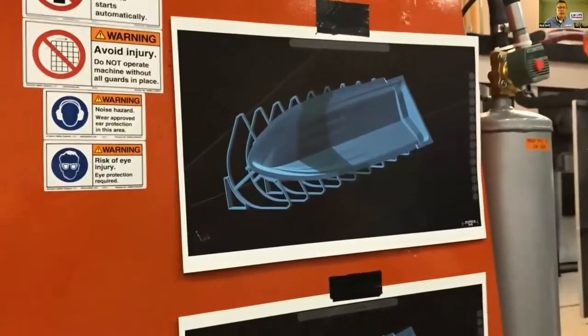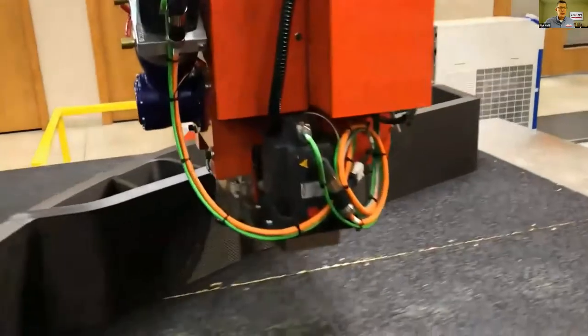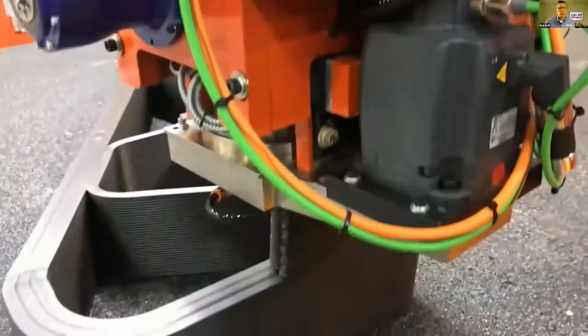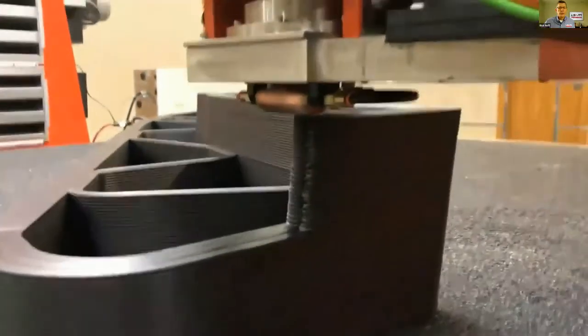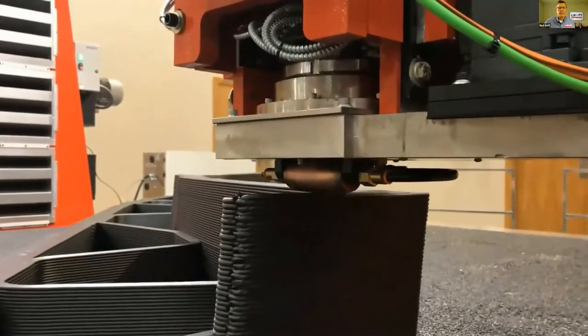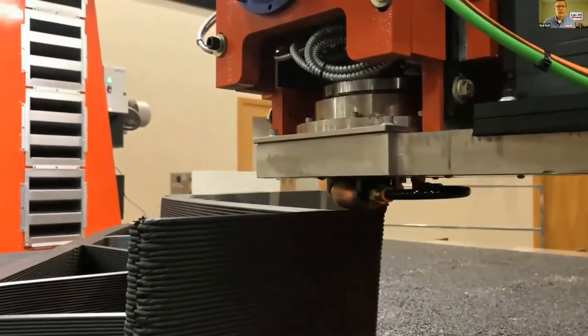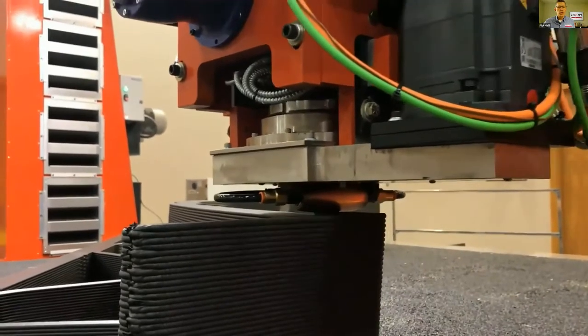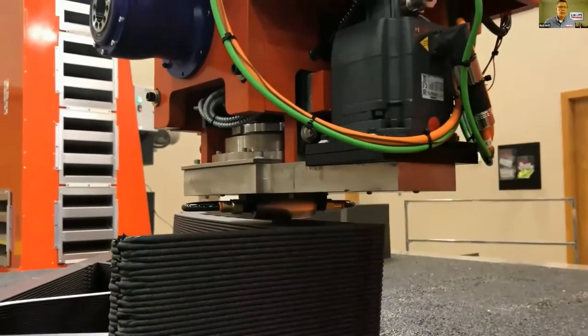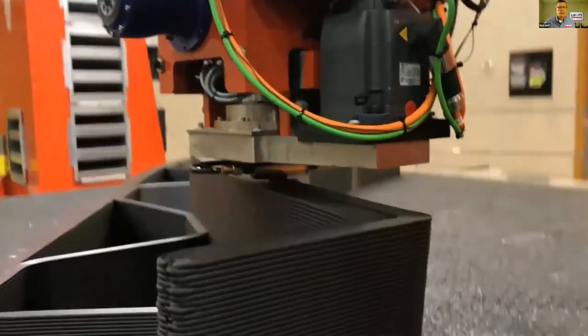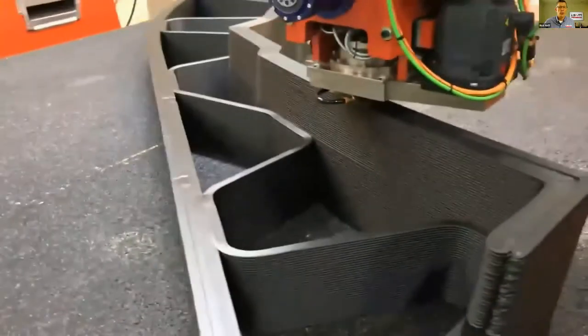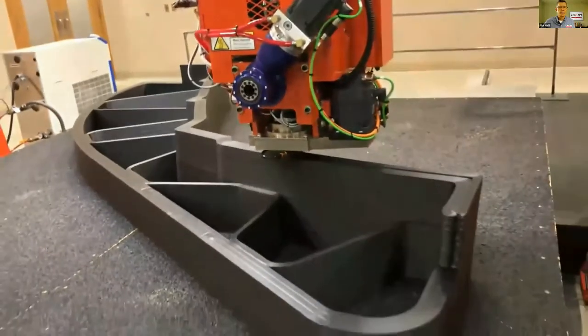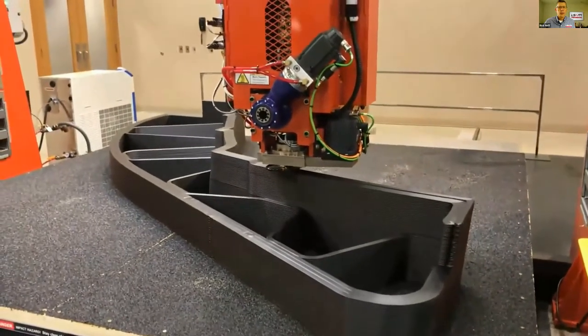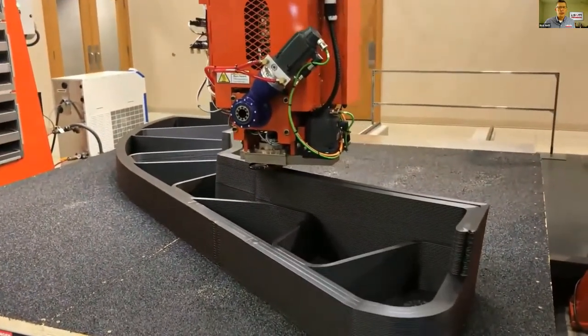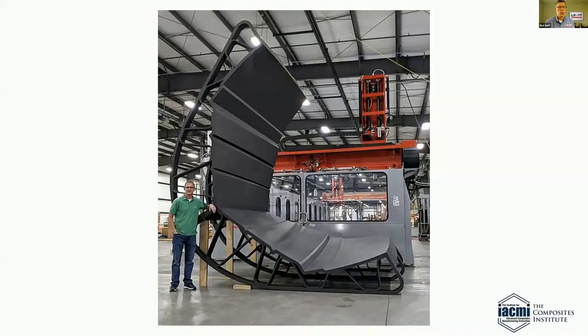This shows the LSAM MT or moving table system printing one of the sections for this tool. And you'll notice that the printing looks like it's very slow. This is about as slow as we can run the LSAM. And the reason why it's so slow is because there's not a lot of material in each layer. So we have to give it plenty of time to cool down before we put the next layer on top. And when we take these pieces and start to stack them up, this is what the mold looks like.